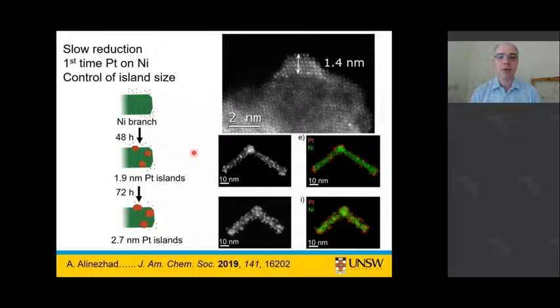So Ali was the student who did this work. He put his branched nickel structures into our Fisher Porter bottles. He put in some platinum precursor and decomposed the platinum precursor. And as you can see, he waited a couple of days and then he looked at what it made, and he'd made these very small islands. This is a dark field image, so you can see the brighter platinum.